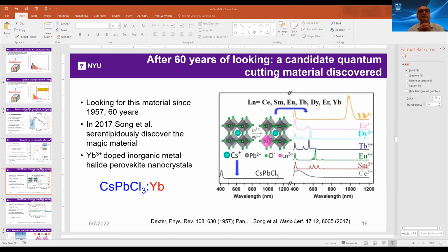If the blue to near infrared conversion ratio were different, would that change the Shockley-Queisser limit? Yes. Basically, anything above 100% will allow you to surpass the Shockley-Queisser limit.